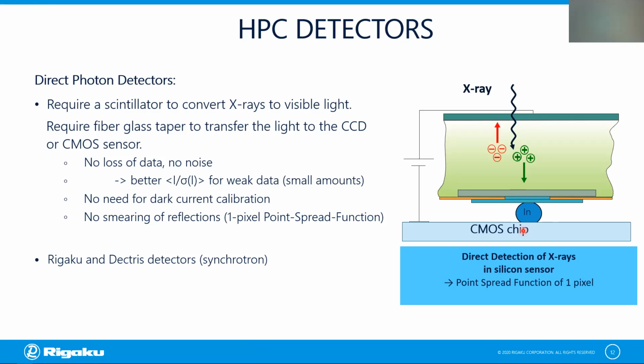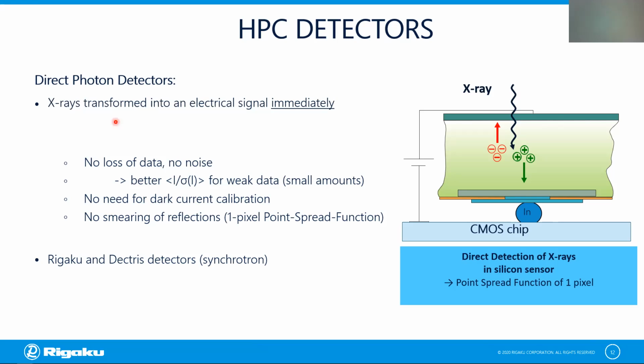and that's how we keep each pixel isolated from its neighbors. As a result, where a CCD or CMOS detector will need a scintillator and a fiberglass taper even before photons are transformed into an electrical signal, here we don't need those things because, again, X-rays are transformed into an electrical signal immediately. The consequence of that is that there's no loss of data. There is virtually no electronic noise also, and that will greatly improve the I over sigma statistics on your data. And of course, this is especially important for weak data.